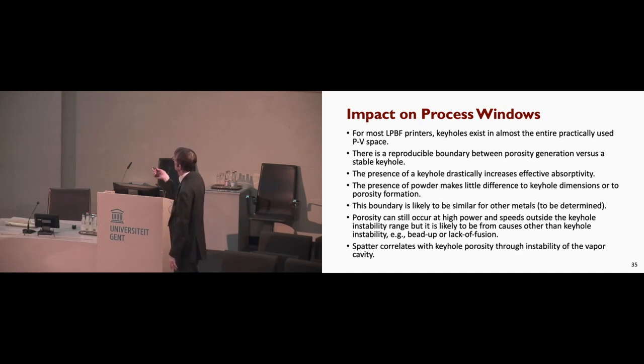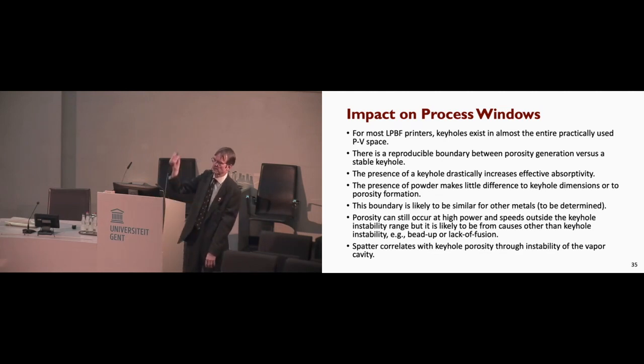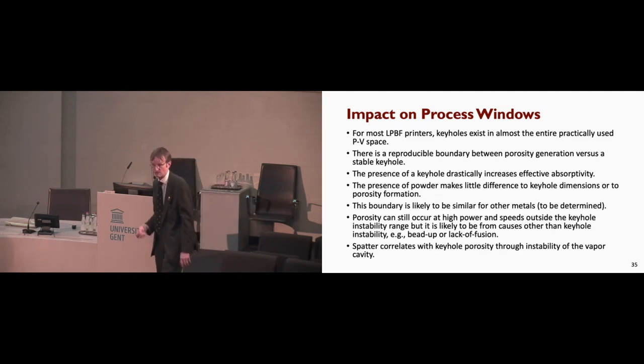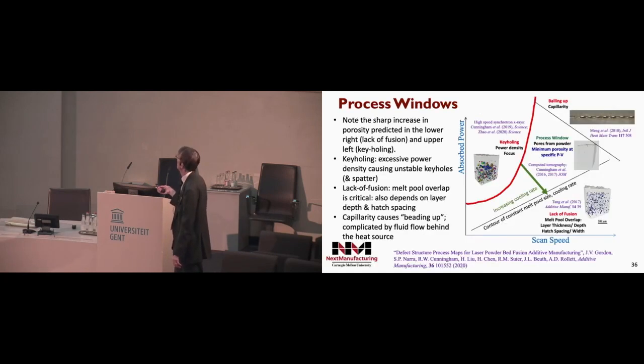Now, there are a number of associated problems. So there's something called spatter, basically droplets of liquid popping out of the keyhole. And those correlate fairly strongly with the stability of the keyhole. So we're learning more and more about that. But let me show you what this process window really looks like.